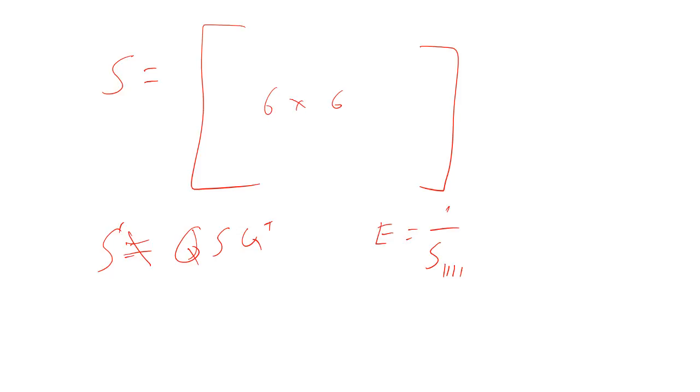So we could transform S to find the Young's modulus in the new frame. That becomes S prime ijkl equals Q_iR Q_jS Q_kT Q_lU S_RSTU.